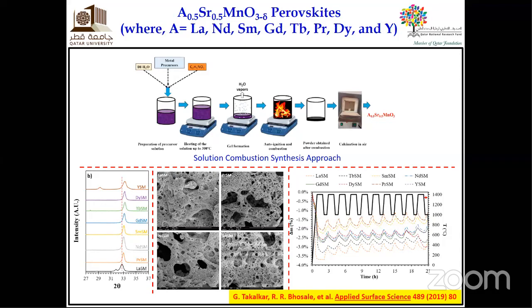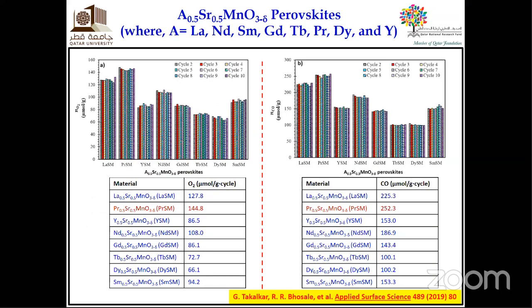Now, the solution combustion synthesis approach has the advantage that it can produce highly porous materials. If you check the SEM analysis, you can see very highly porous materials. And again, we did the TG analysis as we did for the others, same temperature, same conditions, because we want to compare together at the end. Here I didn't put anything in black because all the materials are standalone; there is no base material with which we are comparing. But I put a red color here because that is the most highly efficient material we have. For example, PrSrMnO3 produces 144.8 micromoles of O2 and 252.3 micromoles of CO as compared to the others.